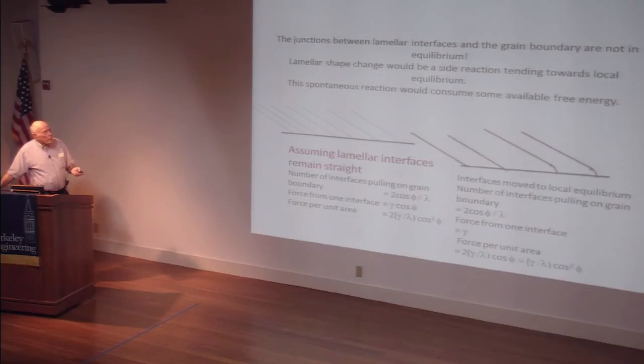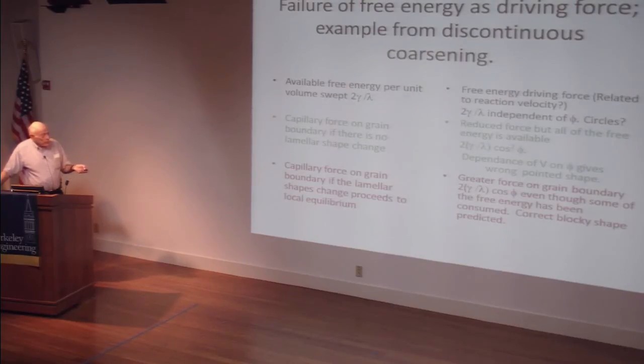Now the next thing is something really strange. If I let the lamellar shape change, bend around, because this is not really the equilibrium angle, I'm dissipating some of the available free energy. But now the lamella are pulling straight up. They're still at the same spacing. And now I have a greater driving force. Even though I've dissipated some of the available free energy in this reaction, the driving force has increased. And that's what the situation is.